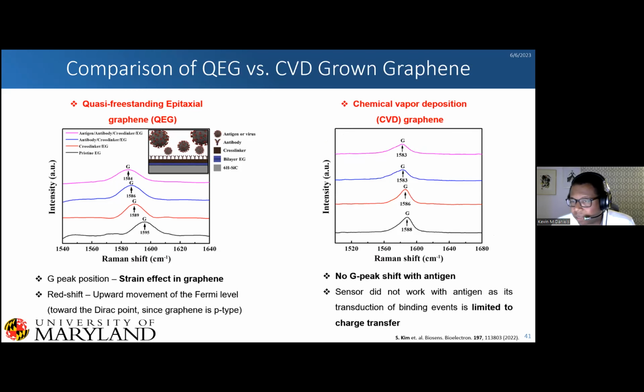And we compared this to just really, really high quality chemical vapor deposited graphene. And after putting down our antigen, we didn't see an effect. And so we believe the sensor didn't work because CVD graphene is limited to charge transfer only. So this is looking at the femtogram per milliliter kind of range. So many, many bindings happening.